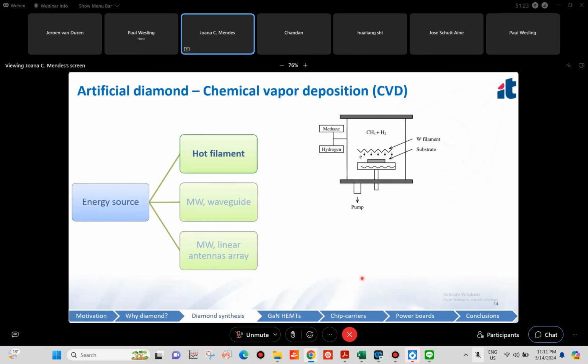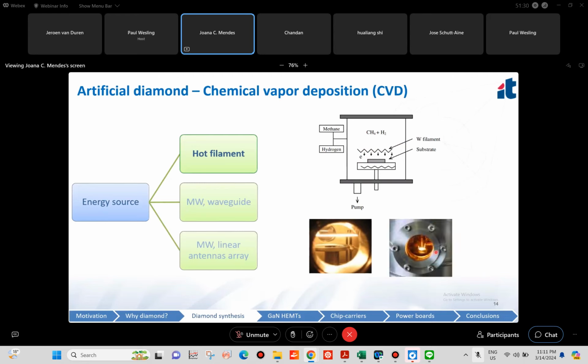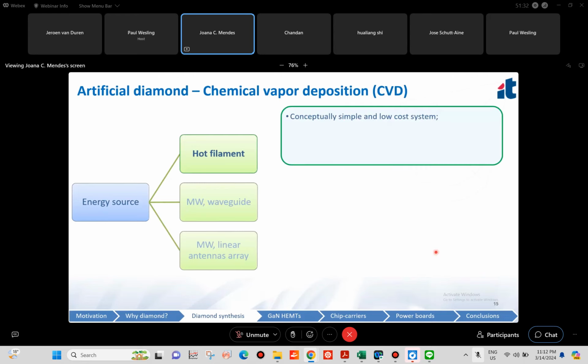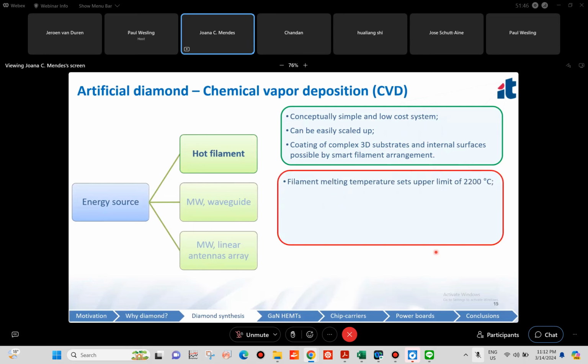For instance, hot filament, it's a very simple system. Here you just see a filament, which can be straight filament or a coiled filament. It's very simple. It's a low-cost system. It can be easily scaled up because we just add more filaments in parallel, for instance. We can use it to coat complex 3D substrates and internal surfaces by arranging the filaments properly. However, the filaments melt, so typically they are used at a maximum temperature of 2200 degrees C.